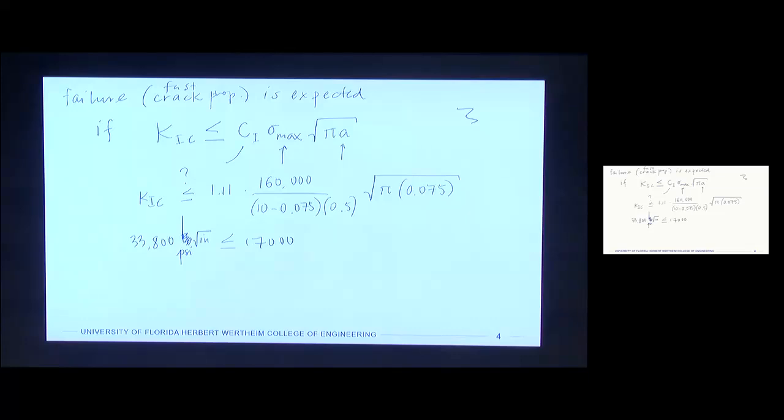Okay. So this turns out not to be true. So our crack is not of sufficient size to cause catastrophic failure. That means that this thing can continue in operation, and it should experience steady crack growth until it reaches some critical size. So what will be that critical size? Well, all we did in this was we plugged in all our numbers and checked it against the K1C.